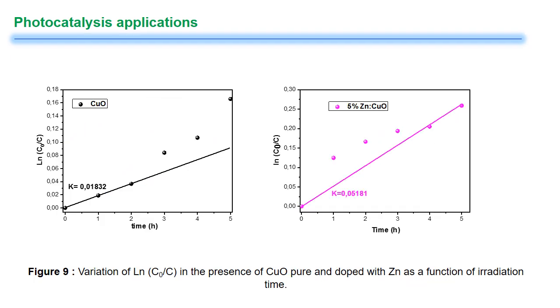The following figure presents the speed of degradation of orange G in the presence of our films. It can be seen that the degradation of orange G increases with the addition of doping.